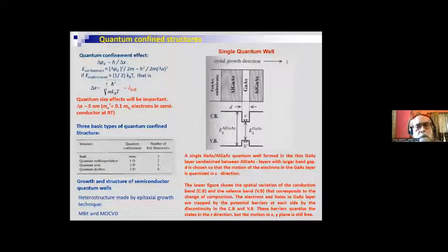And for the quantum confinement, we can actually see from the uncertainty principle that we can immediately get the momentum. The uncertainty in momentum is h divided by delta x, where delta x is the uncertainty in position. This is the very basic uncertainty principle, and from there we can convert the momentum in terms of h cross. Energy we know is p square by twice m. So the confinement energy comes to about h cross square by 2 m delta x square, where delta x is the spread in the value of the position of the electron in the quantum box.